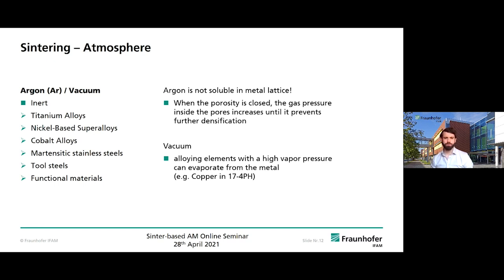But you can't sinter all materials in high vacuum because, for example in 17-4 PH, you have elements that have a high vapor pressure and then they can evaporate from the metal matrix. So if you have these kinds of materials, partial pressure can be an option, but partial pressure is also possible for the other two gases I already mentioned. So that's for the sintering.